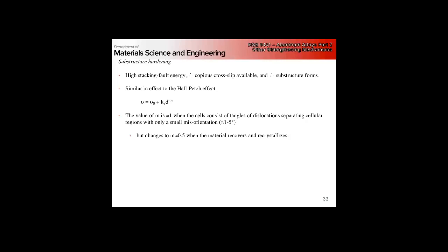You can get around obstacles easier. So much of the behavior of aluminum is completely tied to its high stacking fault energy. So if there's a question that you don't know the answer to and you have to wildly guess, chances are high stacking fault energy will get you partial credit.